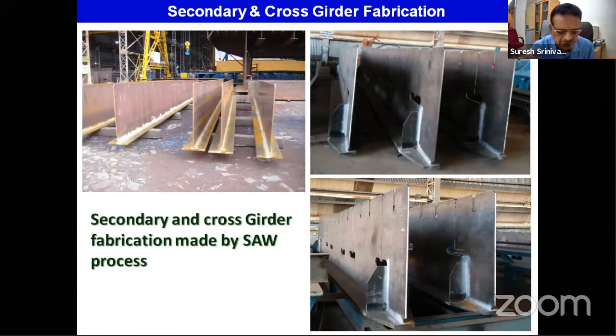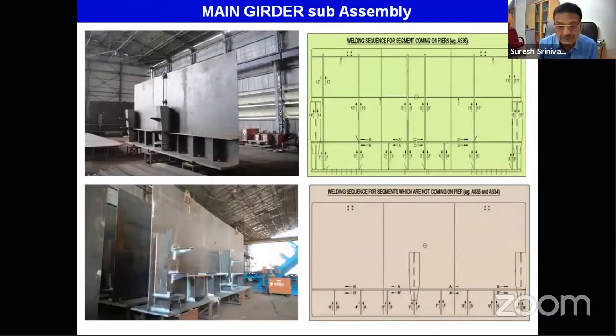Sometimes when the thicknesses went more than 32, 43, etc., we did the root weld with the GMAW, then the back gouging, again did the other side, then continued with SAW process with medium manganese wire and sometimes high manganese wire for getting the strength of the 450C material, 410C material.